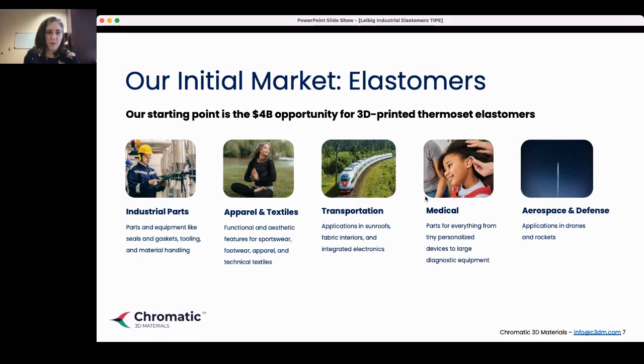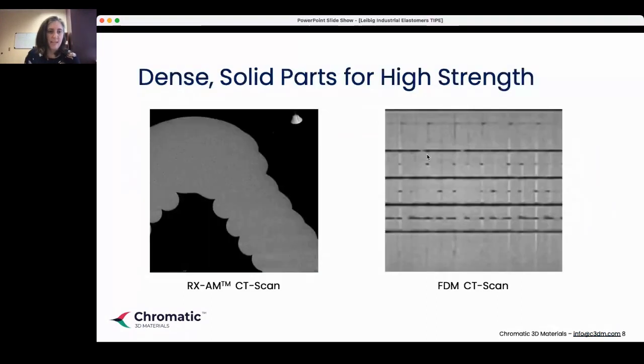So some important features of what we're able to achieve with the elastomers bring it to full industrial strength. First off is that we have dense solid parts. Where we lay down material, there are no voids. And so what you see on the left here is a CT scan of a part, and the CT scan will reveal any gaps or voids. There's really none in our printed parts. If you take an analogous part from FDM, you often have a lot of voids.